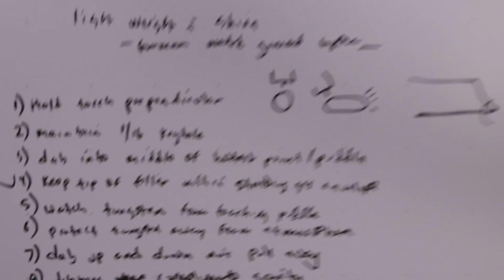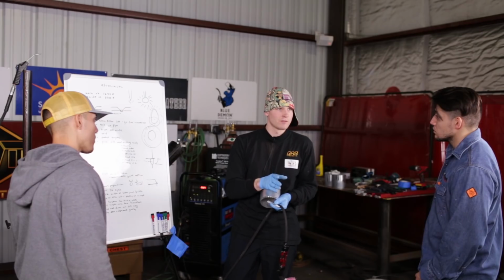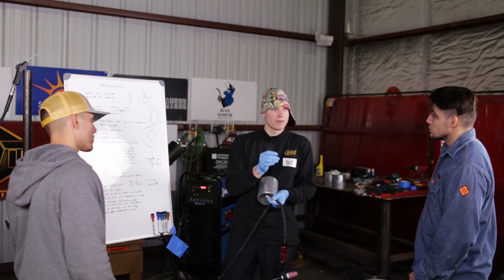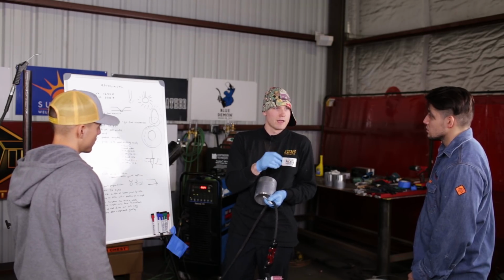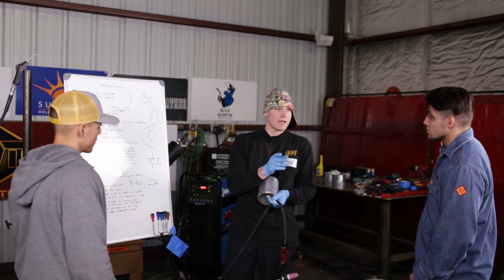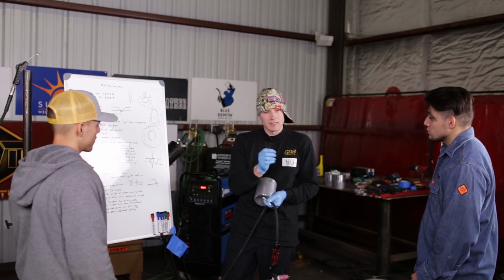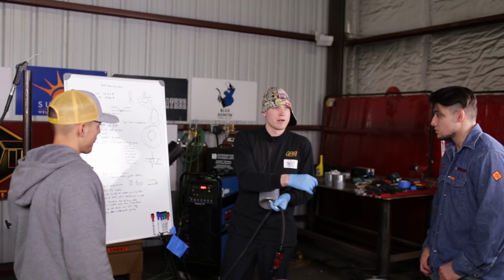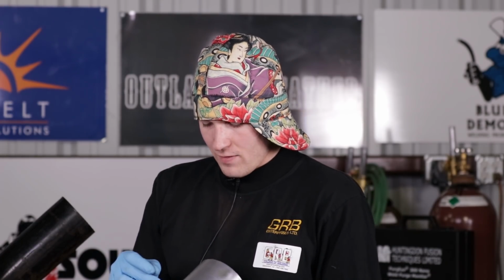The other thing with aluminum is that it is the unfortunate metal that you cannot touch with your tungsten. If you're welding stainless steel or carbon, chrome, you can accidentally touch the tungsten. It's not a huge deal as long as it doesn't get a tungsten inclusion, but you can touch it, oops, okay, and then keep on welding. But on aluminum, if your tungsten gets very close, you'll hear the machine buzz a little bit differently.